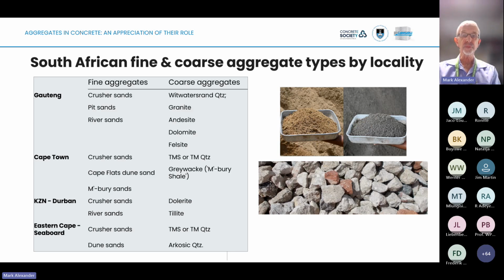And here I've just tried to put down a table where you can identify roughly where you are. Of course, these are the main metropolitan areas. If you're stuck out in the sticks somewhere, maybe this doesn't apply, but you can see in the different major regions the aggregates that are available, both fine and coarse. And it's interesting that certainly Gauteng, which is our richest province, also has the richest option of aggregates. So you can use different aggregates there, and sometimes to good effect. For example, the dolomites are very much in demand if you're doing sewer work, or even for concretes of low deformation capacity, high elastic modulus, low creep, etc. We'll see more of that later.